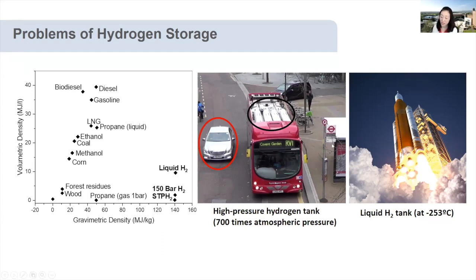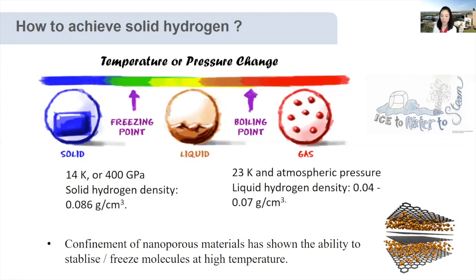Conventionally, hydrogen is stored either in high-pressure hydrogen storage tank at 700 times atmospheric pressure or liquefied hydrogen at cryogenic temperature. The middle photo shows us a hydrogen bus running in London. You can see there are four huge hydrogen tanks sitting on top of the bus. If you compare the size of the tank with a private car, you can see directly where the problem is. And both methods are energy intensive and pose high risk issues.